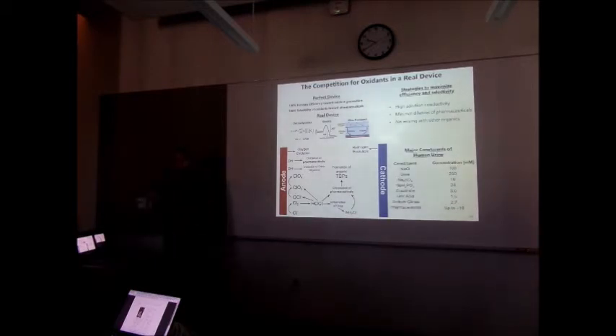So pharmaceuticals are excreted predominantly in human urine, and it has a fairly high conductivity and concentration of these other species. Particularly, the major constituents that we're really going to focus on are sodium chloride and urea. These are the two biggest, the highest concentration things. And you can see that the pharmaceuticals are up to 10 millimolar, but sometimes 1 millimolar, orders of magnitude less than these urea compounds. So the question is, can we break these down when all these other things are present?